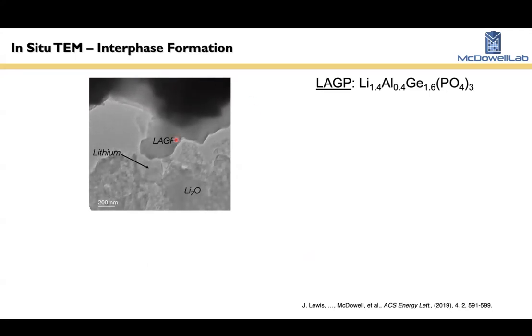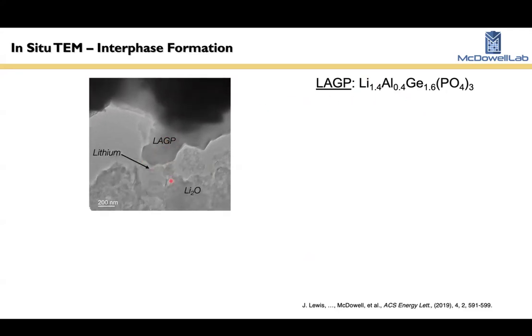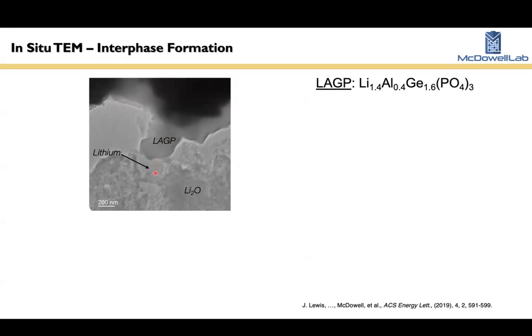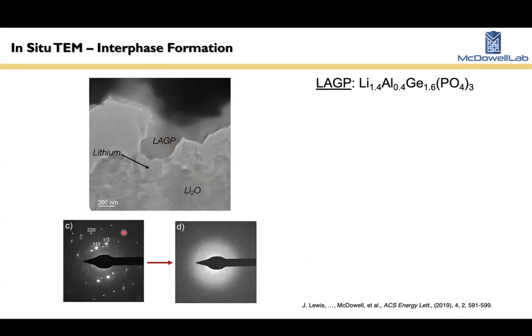This is with a different solid electrolyte material. This is an oxide material, a NASICON type lithium ion conductor, LAGP. Long story short, what we see in these experiments, we actually react the LAGP with lithium in a microscope, and we see that there's this volume expansion and an amorphization process. So the interphase can form and it involves a reaction of the solid electrolyte with lithium, and it can significantly change the structure and properties of this material, as shown here.